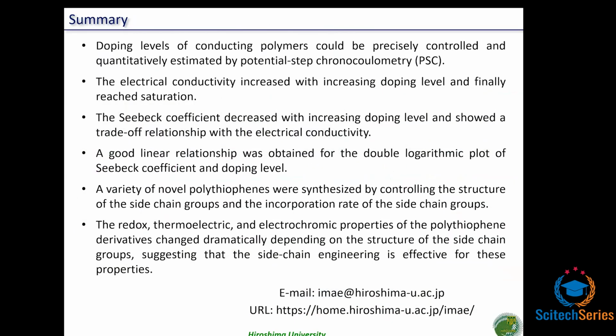Doping level of conducting polymers could be precisely controlled and quantitatively estimated by potential step chronocoulometry. The electrical conductivity increased with increasing doping level and finally reached saturation. The Seebeck coefficient decreased with increasing doping level and showed a trade-off relationship with electrical conductivity. A good linear relationship was obtained for the double logarithmic plot of Seebeck coefficient and doping levels. A variety of novel polythiophenes was synthesized by controlling the structure of side chain groups and the incorporation rate of the side chain groups. But this content is skipped in today's presentation.